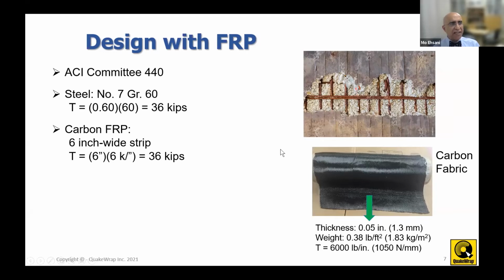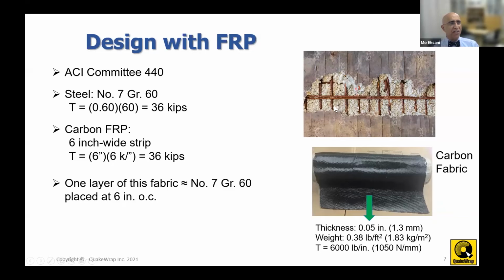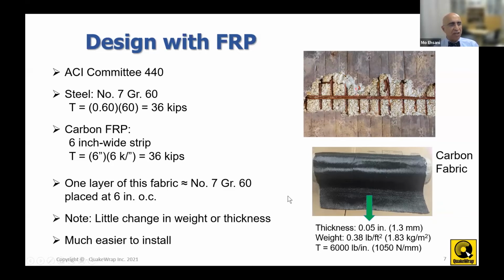So really the comparison of these is that 6 inch of this fabric gives you the same force as one of those reinforcing bars. So basically, if you cover your wall with this layer of this carbon fabric, it is the same strength as if you were putting these number 7 rebars in your structure. And as you can appreciate, of course, this is very thin and it goes on very easily. So construction is really easy. And then, of course, you have an impervious layer on top of your structure that prevents it from corrosion.